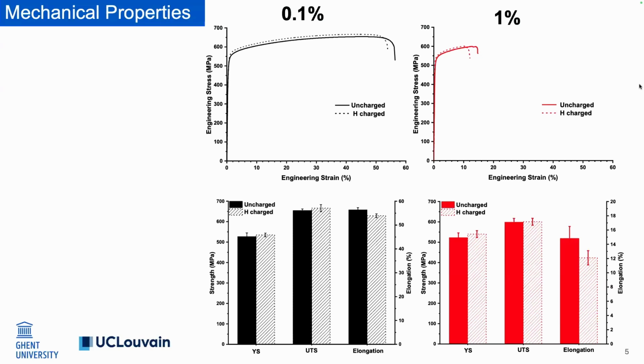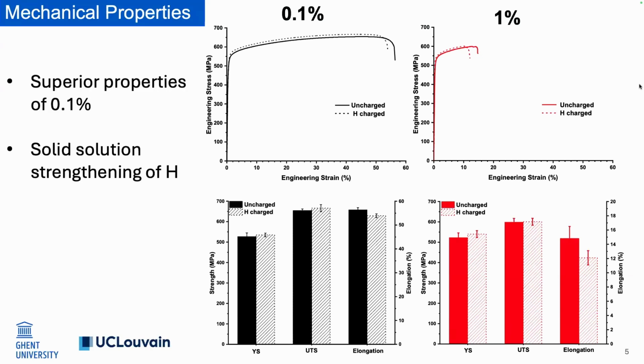This is the engineering tensile stress strain curves of those batches in uncharged and charged condition. The first point we can obtain from these graphs is the mechanical properties of the material with lower porosity fraction are much better than the other one. And there is a slight increase in tensile properties, yield and UTS, which is linked to the solid solution strengthening of hydrogen. And also the ductility loss for the first batch is quite lower than the second batch.